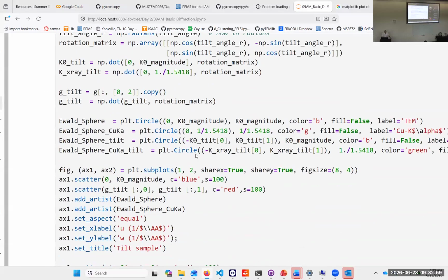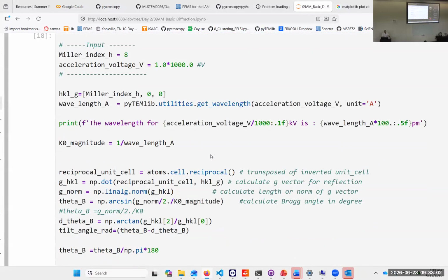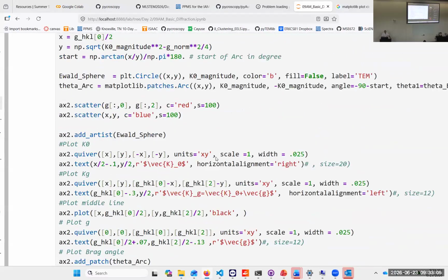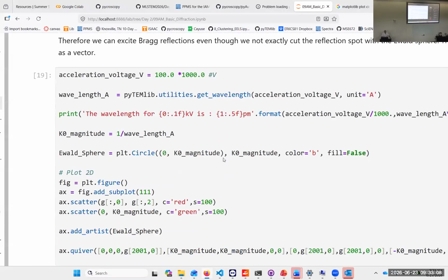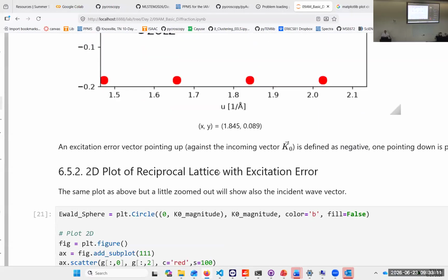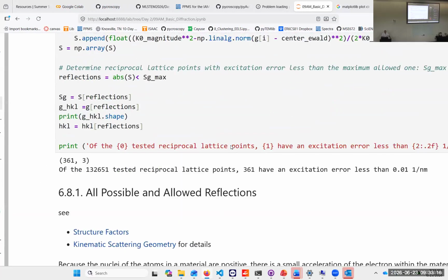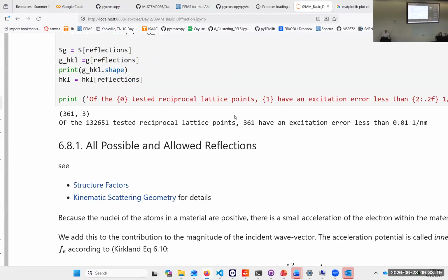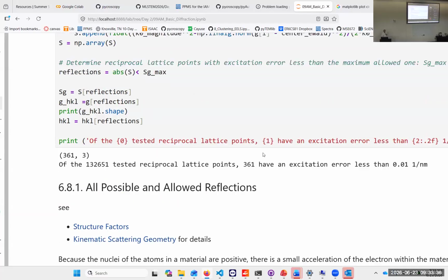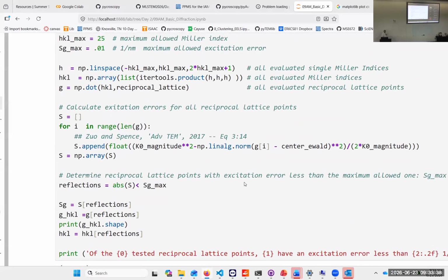So the form factor is the probability for an atom to scatter at a certain angle. And then in a crystal, we have many of those, and they introduce a phase shift. So we have the structure factor and the form factor. The structure factor is the assembly of that. I'm not going too much into that. The form factors are tabulated.